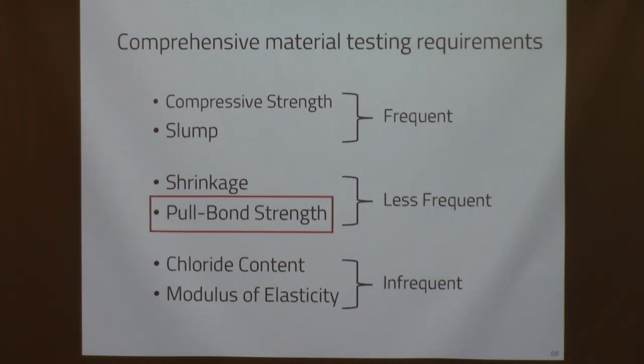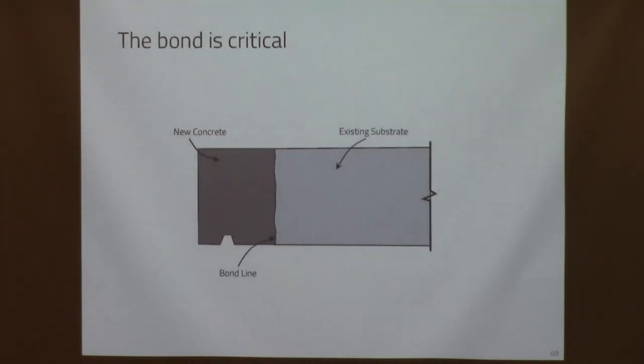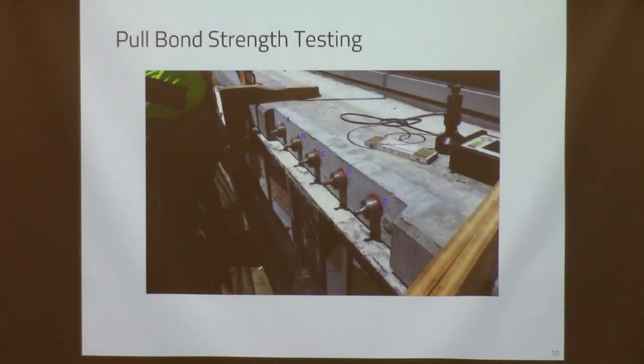So we did frequent tests on the top two just for quality. We did less frequent tests on pull bond strength, and I'll show you some of those, and then very infrequent tests really at the beginning of the repair project on the last two. So bond is critical at that bond line between the two. And the way we measure bond is using these discs. The inspector would go up and tell the contractor, block out this area, this is where I'm going to do some pull bonds.